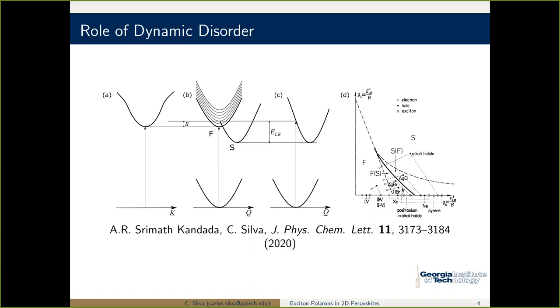But metal halides, here silver chloride and silver bromide, are all in this regime where structural variables, temperature, and so on, bring us across some transition between self-trapped and free, and we're always to some degree bound to the crystal lattice. So the excitation is dressed by the lattice to some degree by a local deformation. The electrons and the holes are pulling and pushing ions very close, and this is a dynamic lattice with normal modes. This is distorting the lattice around the excitation, but there are also long-range couplings that interplay, which gives us a very complex landscape of the excitation. So this is the idea, and it's not only static, but dynamic. It's a highly dynamic system.